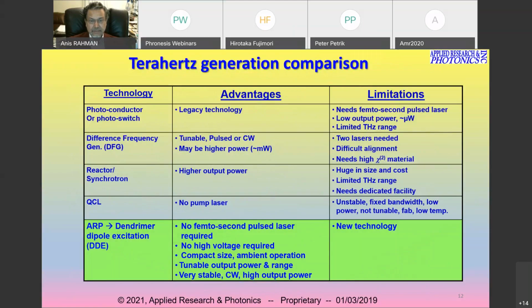So we use terahertz, and T-ray is important because it can penetrate through a lot of materials, solid, liquid, etc. So it allows us to see not only on the surface, but also below the surface in the non-destructive mode. And there are more than one ways of generating terahertz. We specialize in dendrimer dipole excitation, which is a new mechanism invented by our company. And it has quite a few advantages.